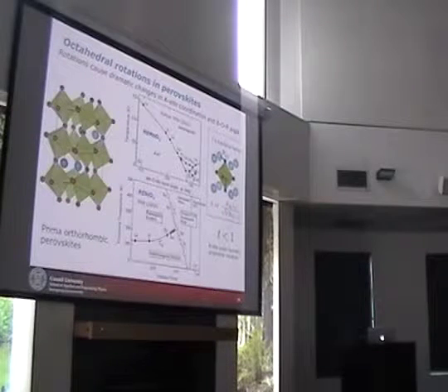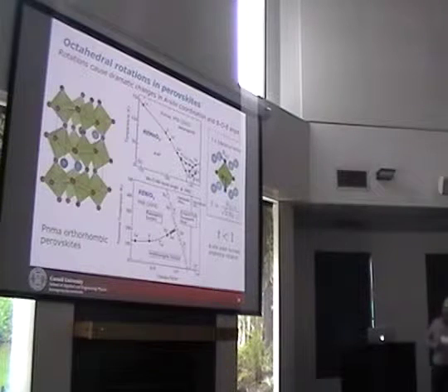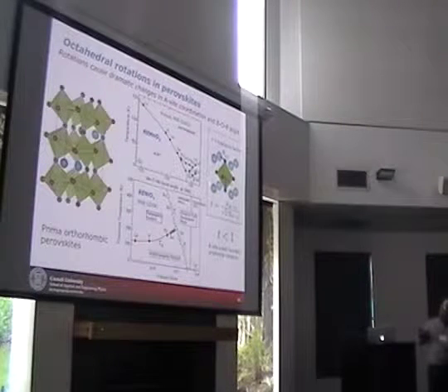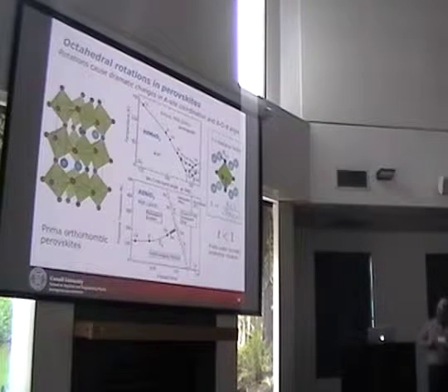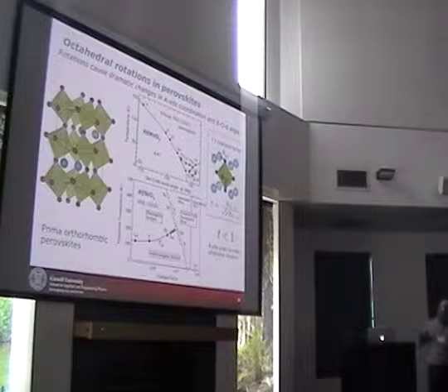And that's what we're showing here. As the A site gets smaller, the tolerance factor gets smaller, and the system distorts more and more. These very subtle rotations completely control the correlated valence states in these materials. We can completely tune between different magnetic states in this rare earth nickelate case, completely tune from, this is the lanthanum